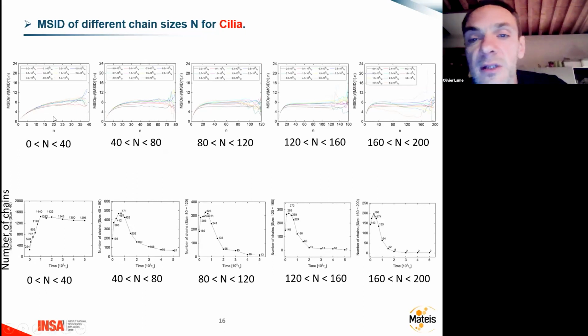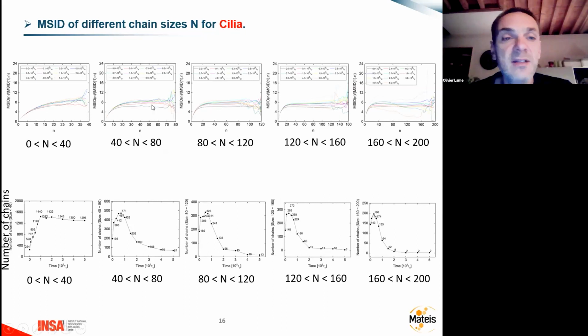So here we have the MSID, the internal distance of the cilia, the pending chain, in the amorphous phase, but depending on the size of the cilia, because the pending chain can have a size in the amorphous phase of 0 to 40, or at the maximum 200, because the size of the chain here is 200. There is a very small number of big chains, as we can see here at the end, but I will discuss that after. This is quite difficult to read, but the idea is just to compare these different curves to know if they are just a straight line or something different. And as we can see for the cilia, at the beginning and at the end of crystallization, it seems to be more or less the same and more or less horizontal, meaning that the cilia seem to be at the equilibrium, which is quite logical because they are free. The end of the chain is free, so the chain can relax, and then they should be close to the equilibrium.